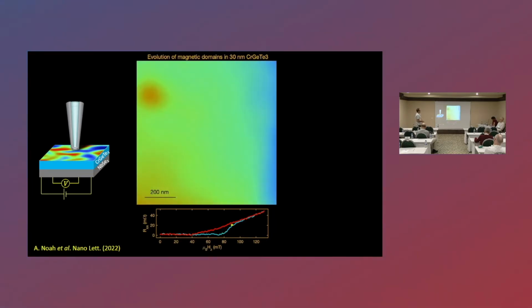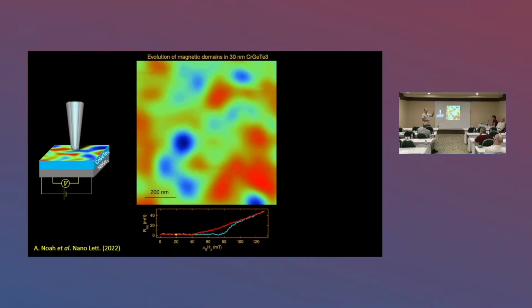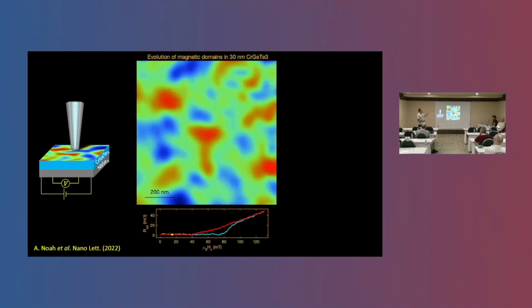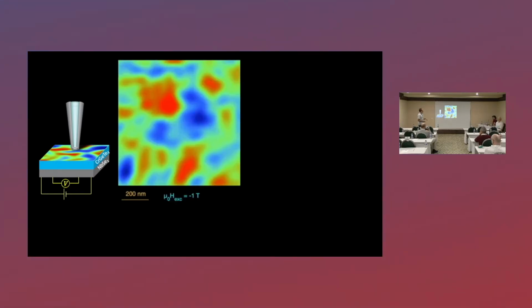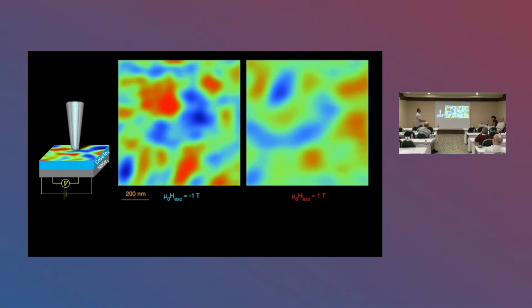So we kind of found an interpretation for this phenomenon, but what we found out is we can maybe use this as a way to probe the magnetic state. Why am I saying this? Because when I look at one image, this image was prepared, taken at zero applied field, but after seeing -1 Tesla. And this image here saw +1 Tesla, but again taken at zero field. So which one is magnetized, which one is not? Is there a net magnetization? It's very hard to say from the image.